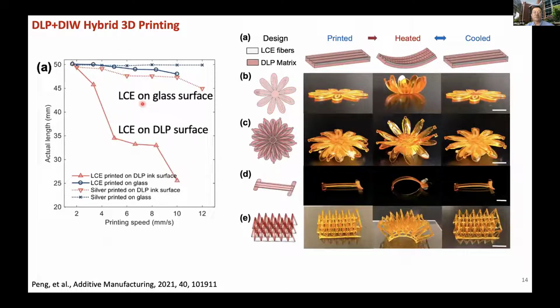So here we printed the LCE on a glass surface. A glass surface is relatively dry, so it's very nice. You can see here, the blue color is LCE printed on the glass, and this is the LCE printed on the DLP. A little bit messed up here. So this is LCE. We print this color, the blue color. This is LCE printed on glass. You can see the LCE actually stays on the glass surface very well.